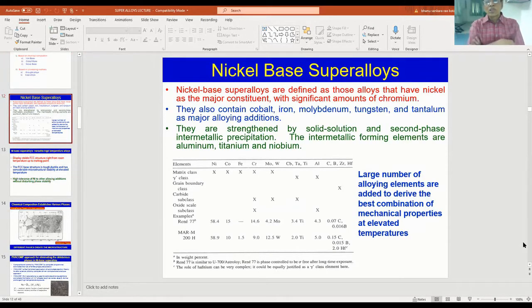This is the most important slide. I said superalloys contain 14 to 15 alloying elements. We will see in nickel-based superalloys what is the role of each alloying element, which is important for the particular purpose for which it has been added. Nickel-based superalloys are defined as those alloys that have nickel as the major constituent with significant amounts of chromium. So nickel is more than 50%, and chromium will be of the order of 20% in order to give you oxidation resistance in the material. These alloys also contain cobalt,